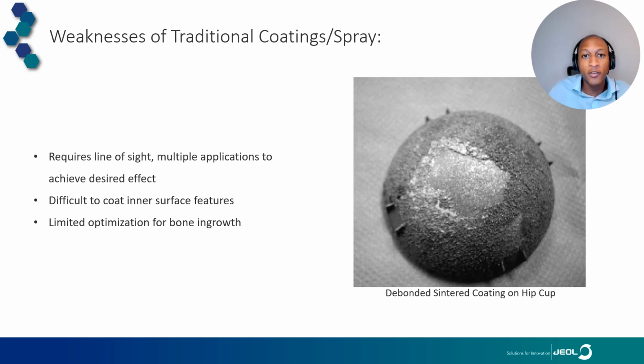However, as you expect, there are certain weaknesses of porous coatings that are traditionally put on traditionally manufactured implants. As you can see from the video, the titanium plasma spray requires line of sight. It's a spray that requires the spray to have a line of sight application to achieve the desired effect. That makes it difficult to apply the coating to inner surface features and hard to get consistent thickness on certain regions. In addition to that, there is limited optimization that can be done for bone ingrowth compared to additive manufacturing lattices. And we'll cover some of the ways that additive manufacturing lattices can be more optimal and be designed optimally, that are quite different to more traditional coatings and spray.